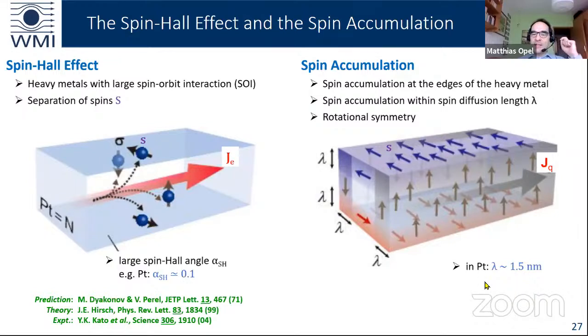With regard to the thickness of the magnetically ordered insulator, we did an investigation in YIG. So we took a YIG sample, a YIG thickness of 100 nanometers, reduced it to 50, to 30, to 20. The SMR effect amplitude was still the same. Then we went down to one single monolayer of YIG, and the effect amplitude still was the same. But when we reduced the thickness further to half the unit cell, then the effect amplitude went down. So that means the effect amplitude reaches, at least in YIG, its maximum value and saturates for one whole unit cell thickness of YIG.